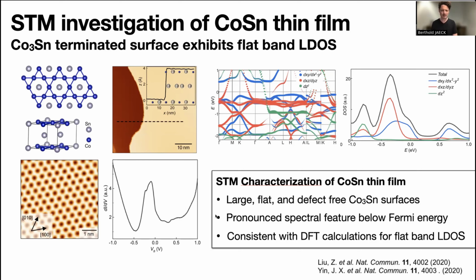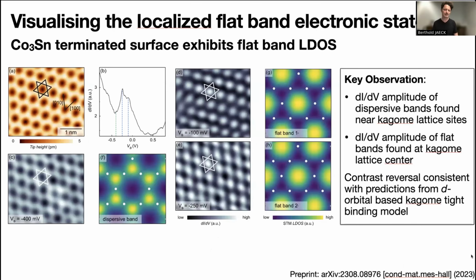So what I show you here now is essentially what has been done before. What I will show you in the following is what is new when we try to directly visualize this non-trivially localized electronic state of a Kagome flat band. The way we do this is to use spectroscopic mapping. More specifically, what we're doing here is now to zoom into this picture I've shown you before, and then record the dI/dV amplitude at different bias set points. For example, when we set our bias voltage to somewhere below the flat band, and it's the same if we set it somewhere above the flat band, we essentially record the following characteristics. Here, the dI/dV amplitude essentially reproduces, in a way, the topography of our cobalt-3 tin surface.